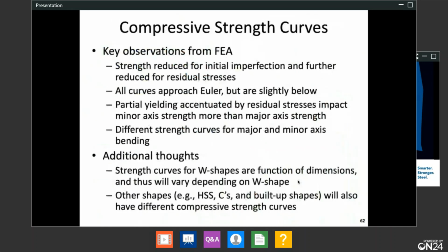So that's what we're doing. Some key observations: yes, the strength is reduced for the initial imperfection, and it's further reduced as a result of the residual stresses and the partial yielding. All curves approach Euler, but it's slightly below. Partial yielding really eats our lunch with respect to minor axis versus major axis. And we could have different strength curves for major and minor. And so the thought is that in reality, every single wide-flange shape at every single length has a different column curve. And that's not only just the wide-flange shapes, the HSS and all of them.